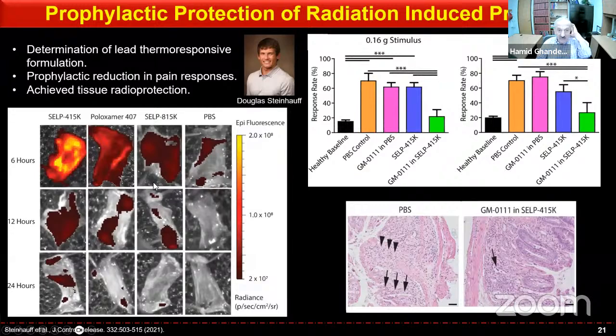If you look at the next slide, it again goes back to the concept of structure-function relationships. The 415K, the one with 4 silk and 15 elastin, gave us the best localization, if you will, in the rectal tissue, and gave us the best reduction in response rate. These are animal tests that we do. We look at pain response, and pain response is a good indication of radioprotection. What you're seeing here is that the combination of the drug with this polymer, particularly 415K, which is shown to localize in the rectal tissue to a higher extent compared to these other systems, gives us the best protection.